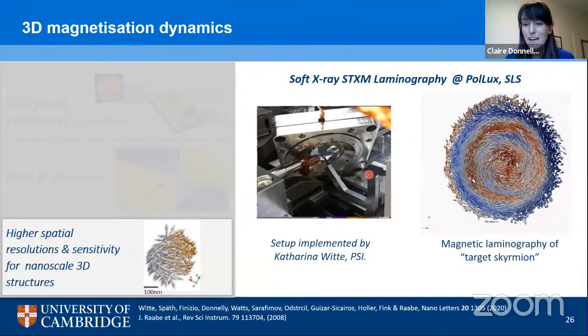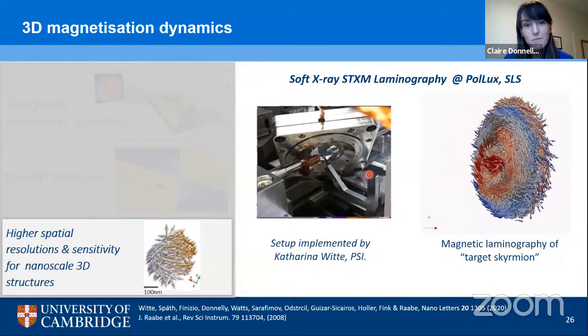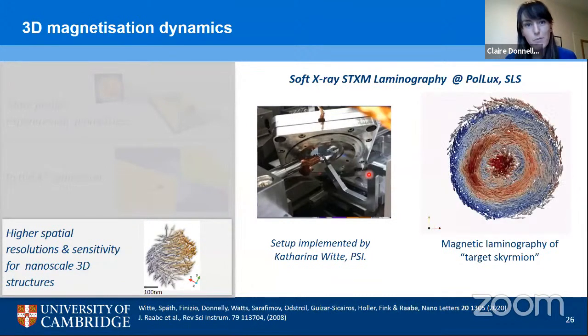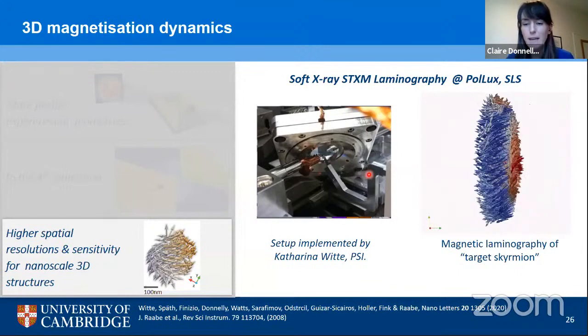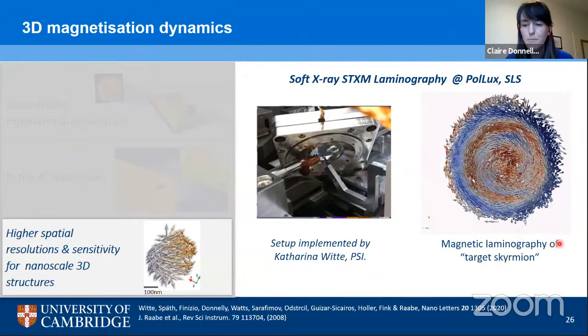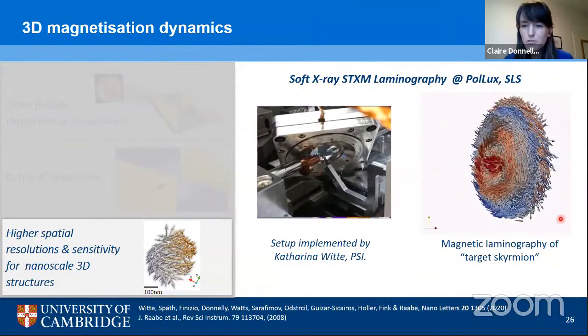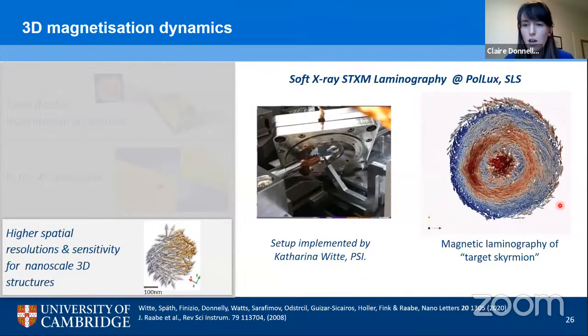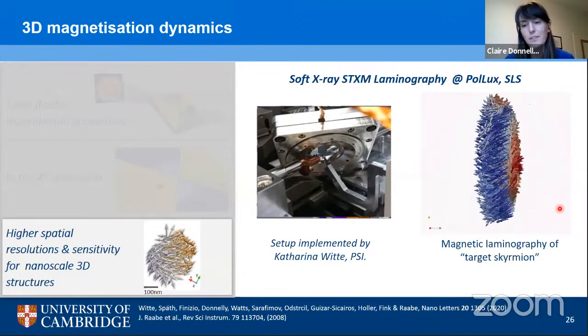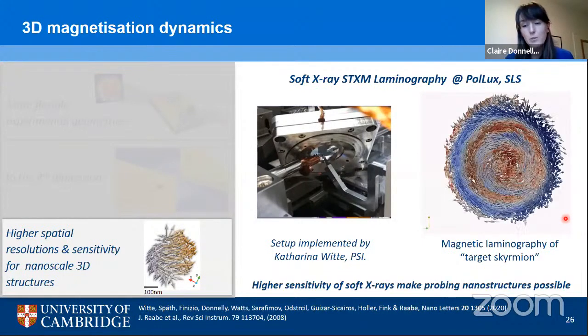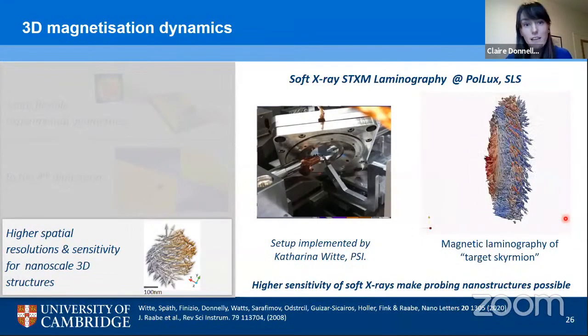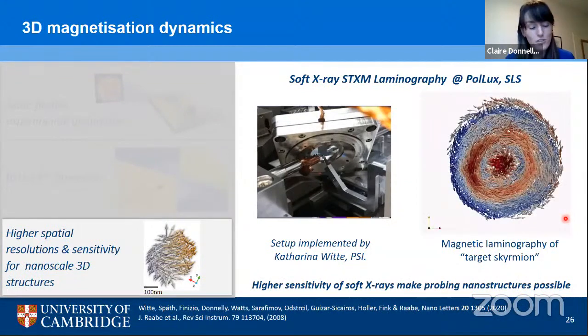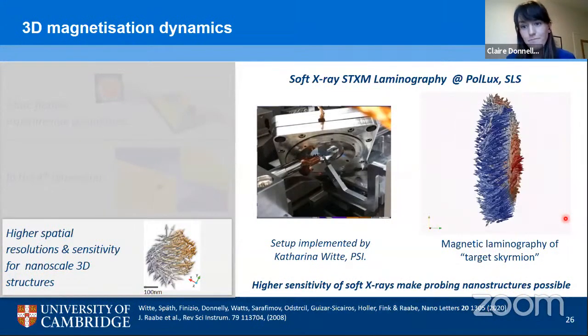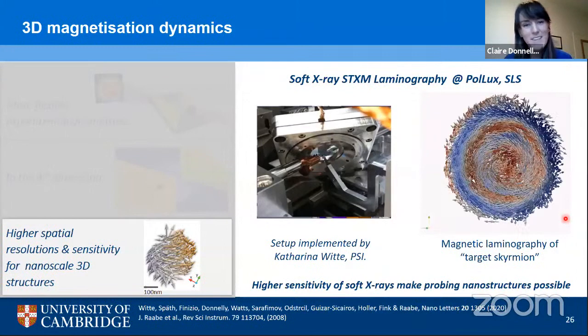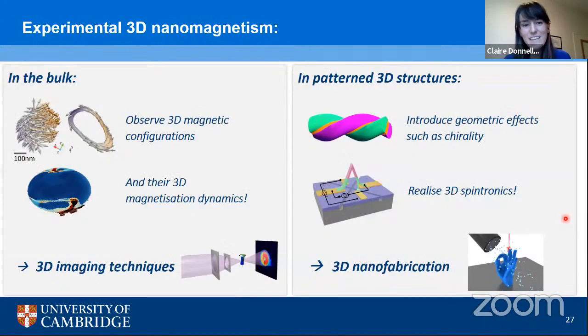And the sample that we look at is a target skyrmion structure, a permalloy disk fabricated by Simone Finizio at the Pollux Beamline. And with magnetic laminography, we're able to resolve the target skyrmion structure with a spatial resolution of sub-50 nanometers, meaning that it's really opening the door to the probing of nanostructures and indeed three-dimensional nanostructures with high spatial resolution.